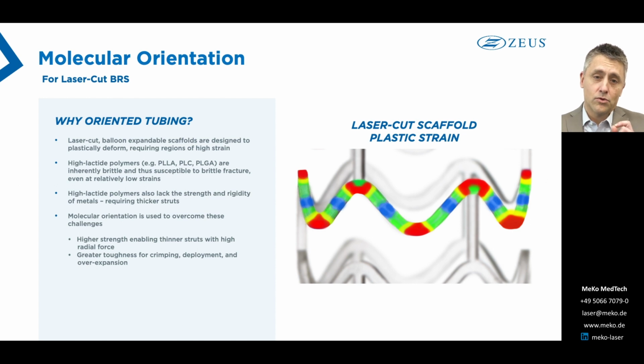So now typical absorbable polymers like PLLA or PLC or PLGA, these are very brittle inherently, so they would not survive such high levels of strain. However, if you remember from our drawn fiber discussions, that molecular orientation greatly increases the strength and the toughness of that polymer. So that was going to buy us two things: toughness to prevent fracture at those high strain regions, and two, high strength for high radial force. That way we can have strong scaffolds but with minimal wall thickness.